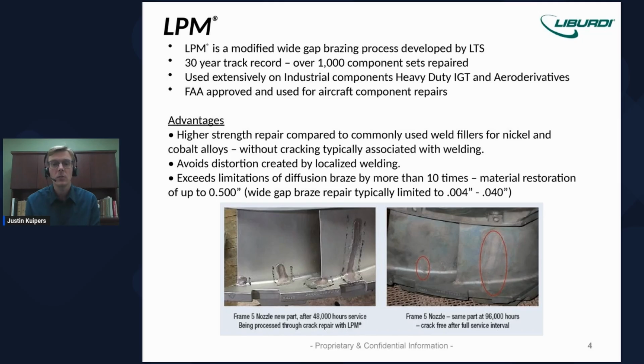In comparison to other wide gap brazing processes, the big advantage of LPM is that it allows us to do much larger gap sizes, so up to 10 times larger gap sizes. Material restoration is possible with LPM up to a ½ inch gap size, whereas with conventional wide gap braze repairs, they're generally limited to between 4 and 40 thousandths of an inch.